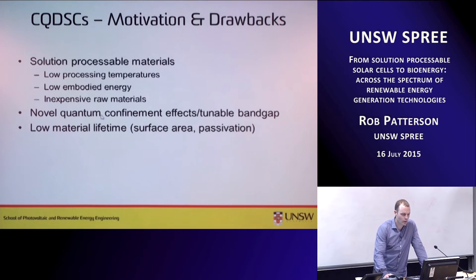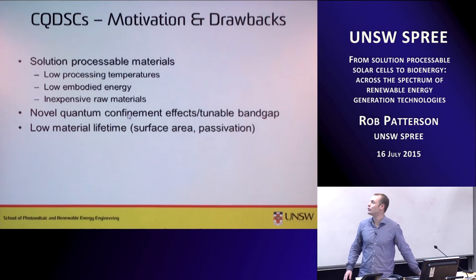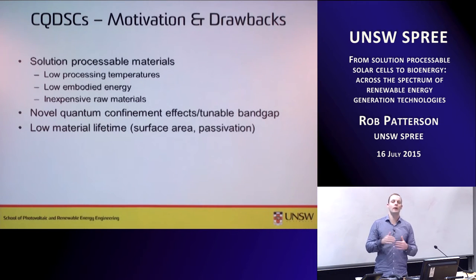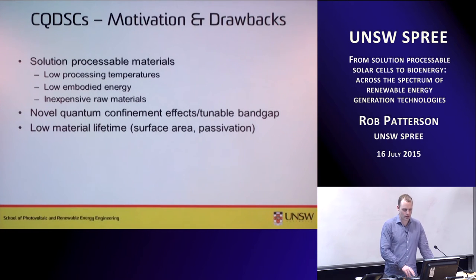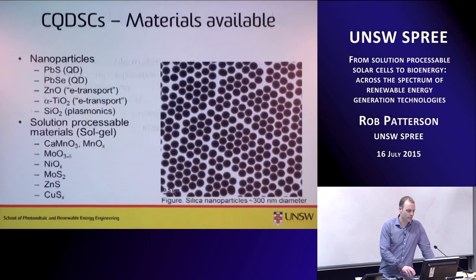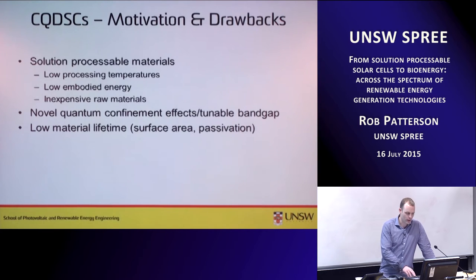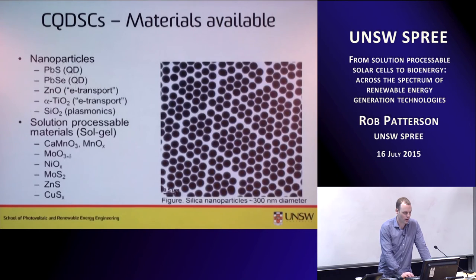The novel quantum confinement effects are the things that we tend to exploit in these materials. So again, as we make nanoparticles smaller and smaller, the band gap gets wider and wider. And for this, we tend to enjoy using materials that have large atoms in them, heavy atoms. We have problems with material lifetime in this cell type, mainly because we have large surface areas, as I mentioned. So passivation is key, and the major efforts in the past 3 or 5 years have gone into passivation. I'm going to talk a little bit about that later.